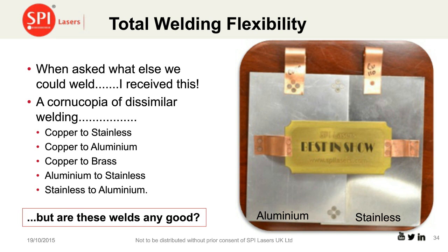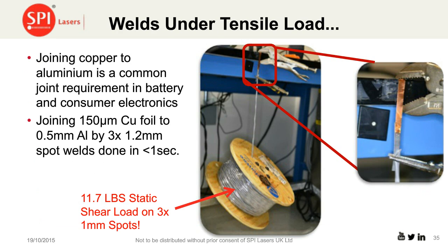They've got examples of copper to stainless steel, copper to aluminium, copper to brass, aluminium to stainless, and stainless steel to aluminium. So quite obviously, my retort to Daniel was, but are these welds any good? To which he replied with the following photograph, which I thought spoke volumes. This is 150 micron thick copper foil joined to 0.5 millimeter aluminium with 3 1.2 millimeter spot welds, all done in under a second.